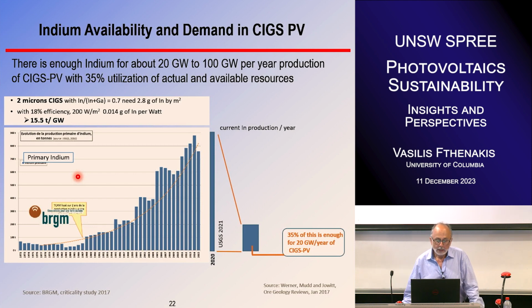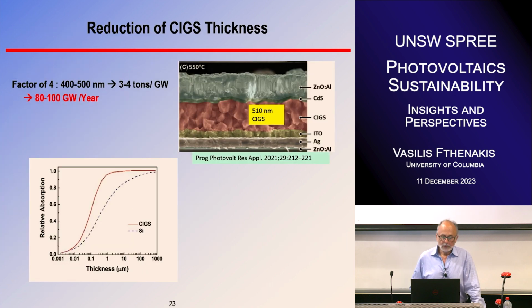So there we have some numbers here from a thin film partnership. The current production is about 900 metric tons per year, and they think that you can use 35% of that. And the current production in solar, First Solar, uses 2 micron CIGS, and that corresponds to about 15.5 metric tons per gigawatt, if you don't have big losses. But if they can produce layers of only about 400 to 500 nanometers, obviously you can get a lot more production for the same amount, like 80 to 100 gigawatt per year.